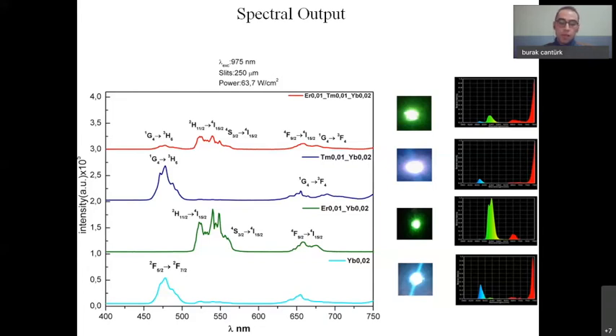The ytterbium has the more turquoise blue, whereas the thulium has more purplish blue. So when it's tri-doped, we can see the peaks that we observed from the co-doped cases as well. And in the tri-doped, erbium again is dominant here, and the emission is green colored.